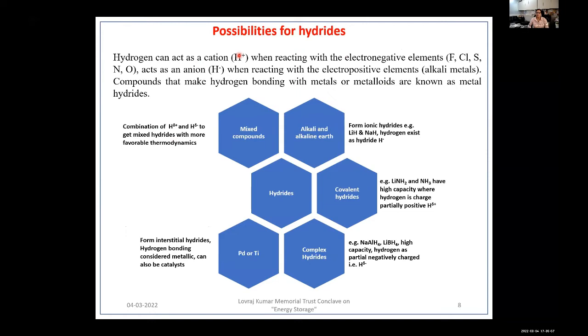Now, among the possible options are metal hydrides. We can have alkali and alkaline earth metals forming ionic hydrides, examples being lithium hydride or sodium hydride, where the hydrogen exists as a hydride, H-. We can have covalent hydrides, like lithium amide or ammonia. They have high capacity, but the hydrogen here is partially positively charged. Similarly, we can have complex hydrides like sodium alanate or lithium borohydride, different alanates and borohydrides, which have a high capacity and a partial negative charge, delta negative. Then there are interstitial hydrides, like the intermetallics I have already mentioned. They can store hydrogen by forming metallic bonds.